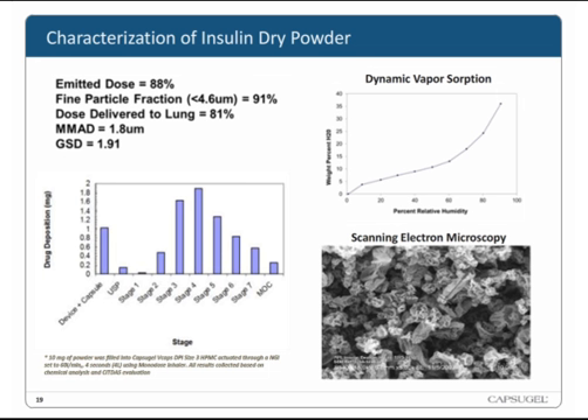And then this is just a beautiful scanning electron microscopy image showing the really shriveled, high surface area, low contact point of the spray dried powder, which means less contact between the particles means less van der Waals interaction and higher dispersibility for a well-performing dry powder product.